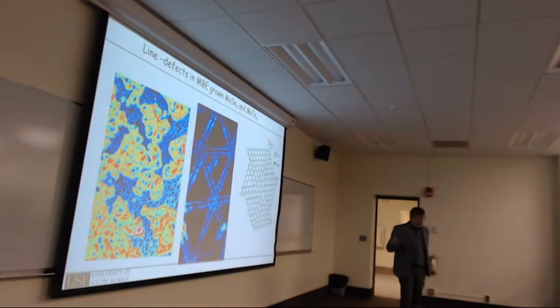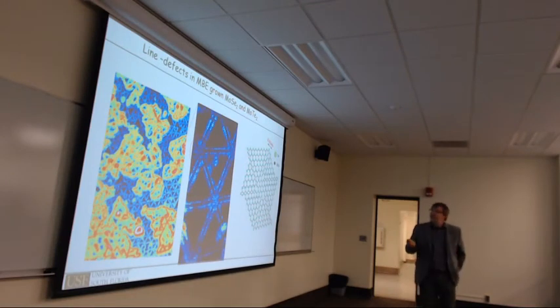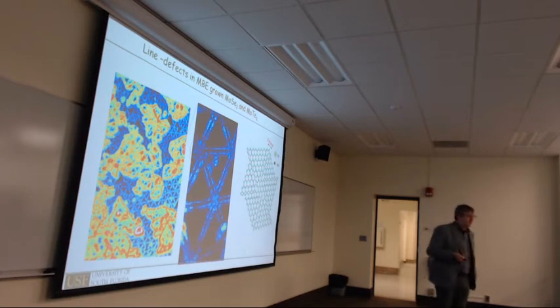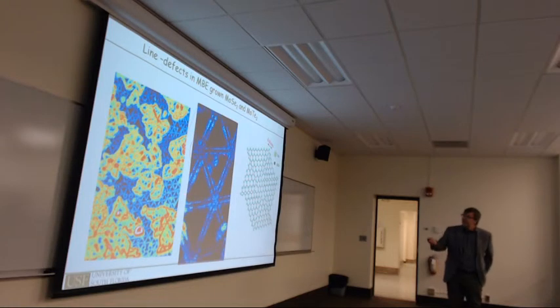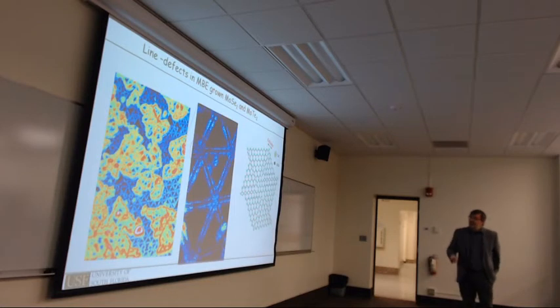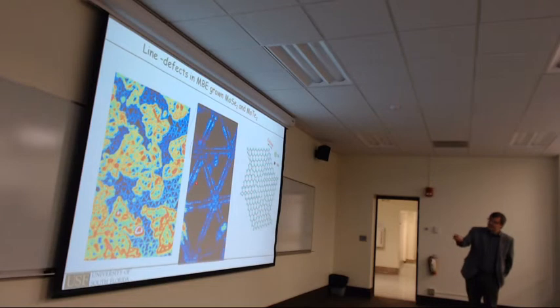And we found that those form very readily if we grow, for example, molybdenum diselenide with molecular beam epitaxy. So the same growth as before, just by co-deposition of molybdenum and selenium on the surface. You get this very dense network of these grain boundaries. And if you zoom in with the STM, you can see that every grain boundary is this double row of bright atoms. And so the model is that you get this kind of pinwheel structure, where the pin and wheel is just alternating grain boundaries.